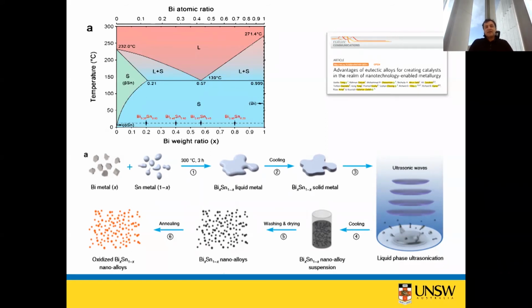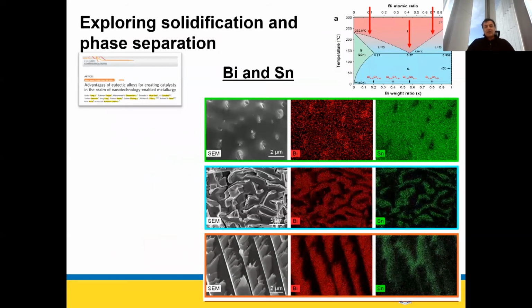So basically, we sonicated everything at a relatively high temperature of 250, 270 degrees. We made these nanoparticles of metals, bismuth and tin in different ratios. We use them as they are, or we anneal them as a photocatalyst. Before annealing and using them as metal, if you break one of these particles and open them and look at them, microparticle, before you sonicate them for too long, you see very interesting classical metallurgy formation of crystals.